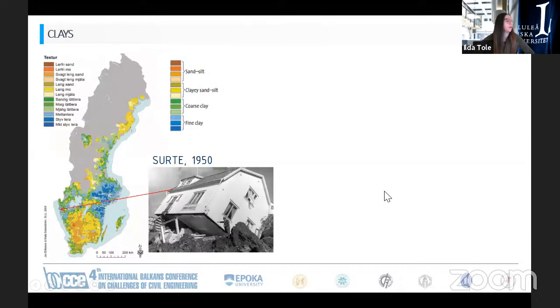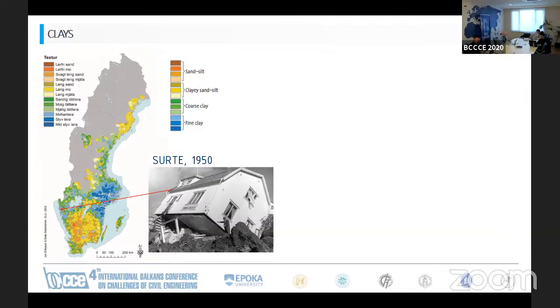Starting with clays, I start from the area where I am living and studying. In Sweden, the presence of clay is not so high, and it is mainly in the south. The main problem in this case is the instability of this material. Often, prior to construction, all this unstable clay soil has to be removed. It is usually deposited next to construction sites or in some area in the neighborhood, generating huge deposits of waste clay. So in this context, the idea is to utilize these clays, activate them, and then further produce concrete to build.